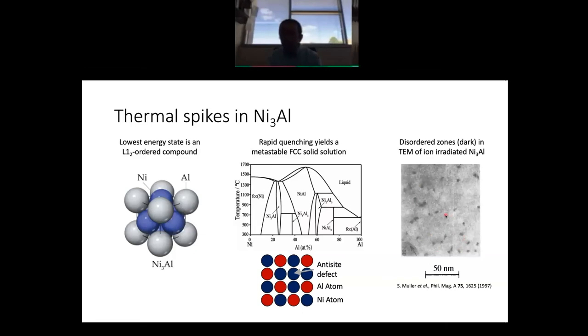And all these black regions that you see here, all those black dots, are actually the frozen cores of thermal spikes. And you can see them in the TEM because those regions are disordered, whereas the surrounding matrix is ordered. And you can distinguish between the ordered and the disordered matrix in the transmission electron microscope. Okay, so you can actually do transmission electron microscopy that colors those two regions differently, but based on their ordering.